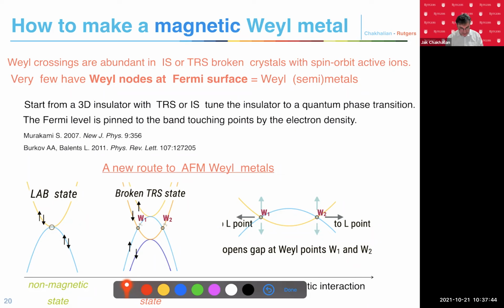What happens here, once it goes ferromagnet or antiferromagnet, and it doesn't matter what temperature, so it could be 100 or 200, is that the majority and minority bands split. And you have no chance not to create Weyl points. If you start with this state and you split these bands, they automatically have these crossings. That's the reason they survive for such a long range. What protects them is really the magnetism. Of course it's spin-orbit as well: the high spin-orbit and the moderate Hubbard U create this very unusual structure which automatically generates these Weyl crossings.